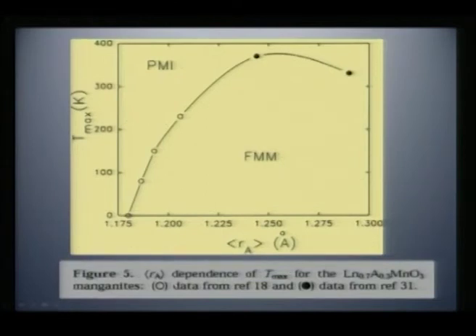Now, this is another figure that I have taken from a paper of Raveau from France. This appeared in Chemistry of Materials volume 10, and this curve also shows a plot of Tc, that is Curie temperature, as a function of Ra, because if you keep on varying the Ra value from 1.17, as you know here it has gone into a paramagnetic insulating state, whereas if you start increasing this way, then you again transform to a ferromagnetic metallic state. So, from a paramagnetic metal to a ferromagnetic metal, the critical tie line seems to be something like this, where you have a critical boundary which separates both these behaviors. So, average Ra is very important.